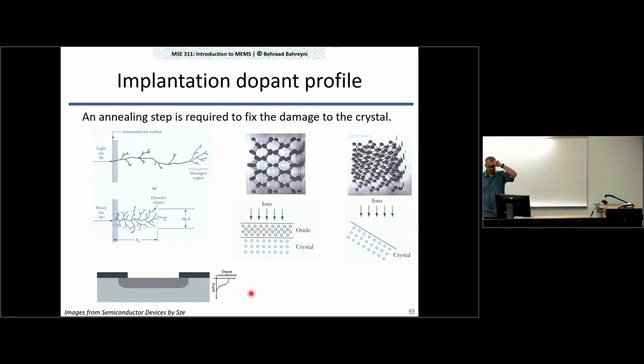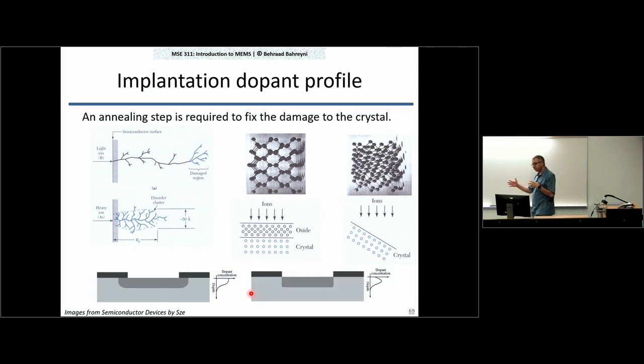So you have damaged your crystal, and then what you normally do after an implantation step is annealing. You raise the temperature so that the crystal has a chance to fix itself, to anneal itself, to heal itself. And after that you have a perfect crystal, but the side effect of that temperature rise is that some of your dopants will diffuse sideways. These dopants are already inside your crystal. You raise the temperature to 1000 degrees, and they start to move about. So you get a little bit of diffusion during the annealing step, but that normally is done very quickly, let's say 10 minutes or 1 minute, or whatever you need to heal the crystal,